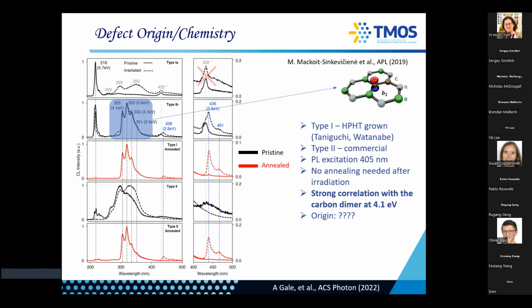But the brightness of those single defects is relatively low, so maybe around 30, 40,000 counts per second. So the visible ones are in the hundreds of thousands, maybe 10 times less. But kind of eyeballing it from the data sets that we had, I don't think there is much difference in the intensity of them as a function of which type you make. Okay, so it's consistent between types. Relatively similar. Cool. Cheers.